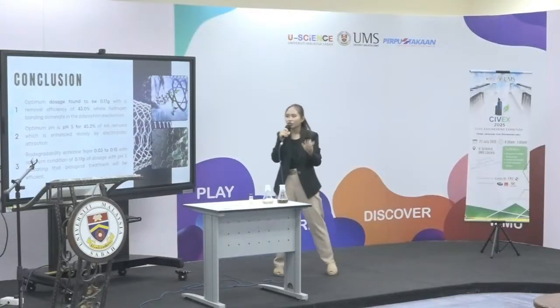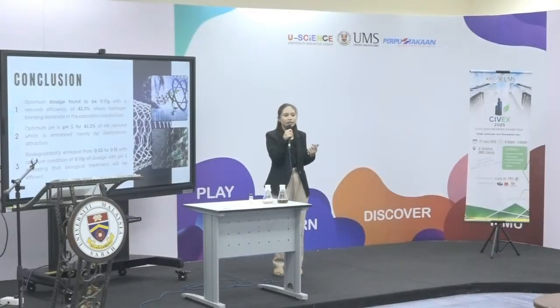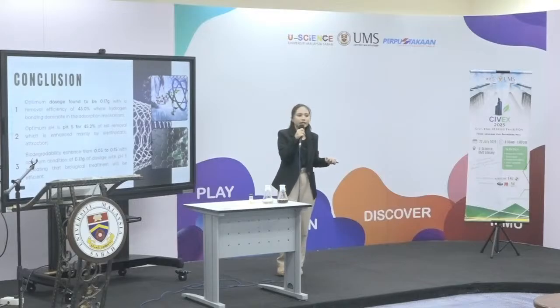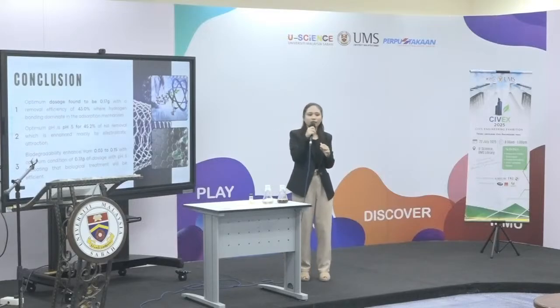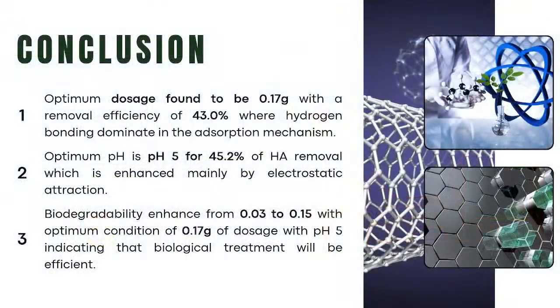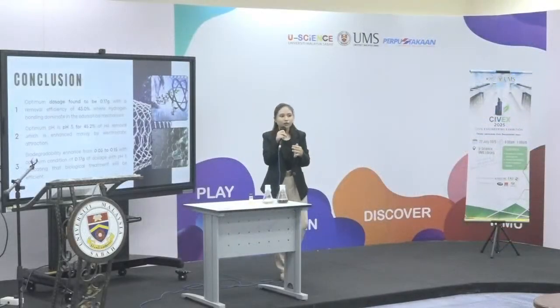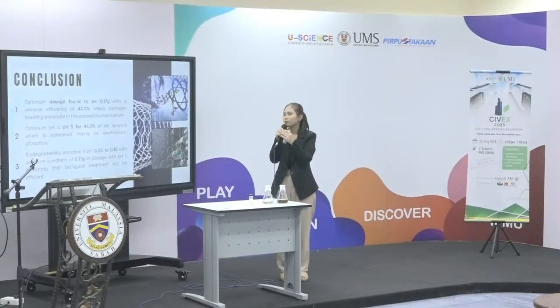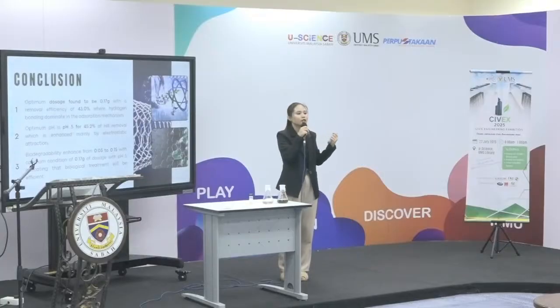So this is the conclusion. The conclusion is we have found the optimum condition is at 0.17 gram at pH 5, and it is mainly due to hydrogen bonding and electrostatic attraction between UiO-66-NH2, the adsorbent, and humic acid. The biodegradability also enhanced from 0.03 to 0.15, which means biological treatment will be efficient after this.